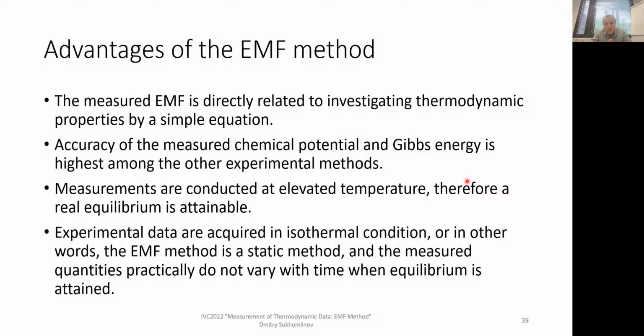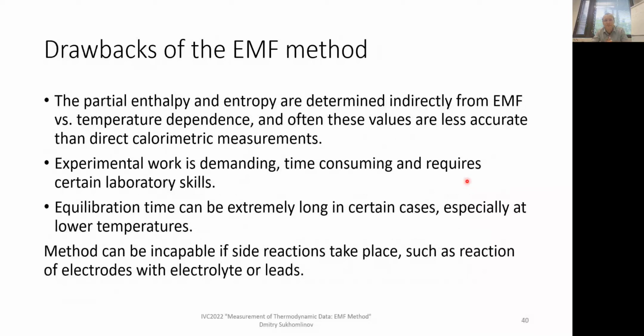And it's pretty accurate. Because it's a static method, measurements are done in true isothermal conditions. When we repeat measurements with circulating cooling and heating cycles, we usually end up with very repeatable results. So it just emphasizes its accuracy. But then, about drawbacks of this method.